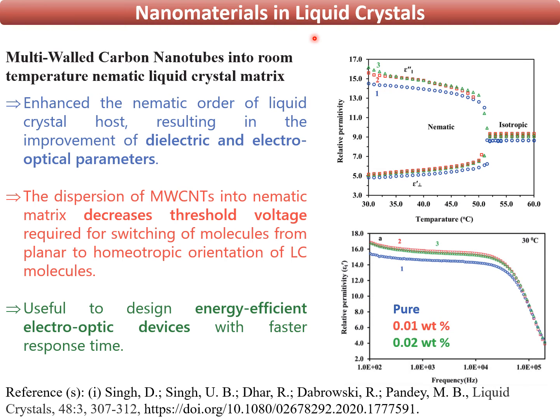In this example, multi-walled carbon nanotubes were dispersed into a matrix of room temperature nematic liquid crystals at 0 weight% (pure), 0.01 weight% and 0.02 weight%. As can be seen in the two figures on the right side, relative permittivity has a higher value in the case of the 0.01 weight% and 0.02 weight% doped samples. It was also found that dispersion of carbon nanotubes in the nematic matrix decreases the threshold voltage. These properties make them useful candidates in designing energy efficient electro-optical devices with faster response time.